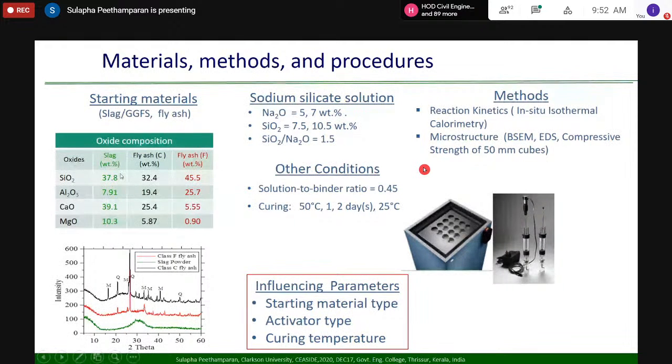Some of them are crystalline, some are amorphous. Amorphous means it has a glassy structure, it doesn't have an order. You can check whether your material is amorphous using X-ray analysis. If you have more amorphous material, it is much better to use it.